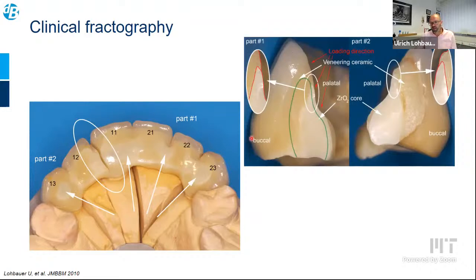We can see the core material. We can see the veneering material. We see a huge pore inside the veneering material. And we can certainly already conclude there is something wrong in the design. So there's a different anatomical design of the core. On this picture already, you see the exposed white zirconia core material and the yellowish or tooth-colored veneering porcelain on